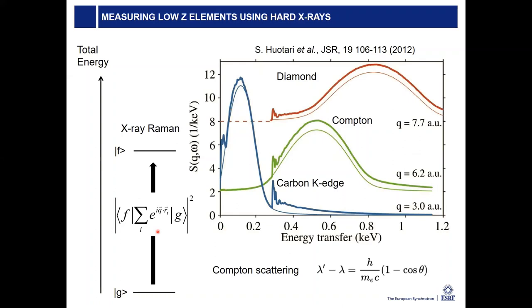I show again here the matrix element that you have to calculate in order to obtain your spectra. This is the study by Simo Huotari at Helsinki, who has very nice papers that explain this Raman scattering. So what you see here, this is the Compton peak, the broad line here. This is measured, I think, at roughly 10,000 electron volts incoming energy. And if you change your momentum transfer, you see how the Compton peak changes.